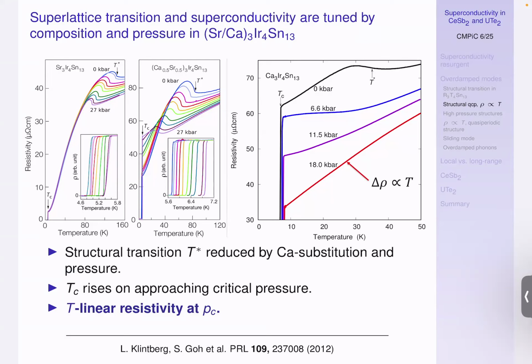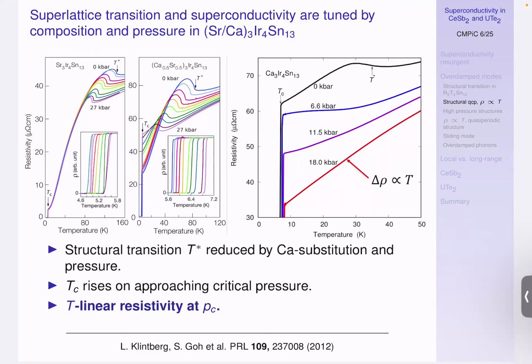If you apply a magnetic field, it suppresses superconductivity, but we haven't really got good data to analyze the power law down here. But there's actually a problem there as well, which is a fundamental issue in a lot of materials like that: applying a field also changes the normal state resistivity. It doesn't just unmask the normal state underneath the superconducting state. If you apply a magnetic field to get rid of superconductivity here, you'll find the resistivity also changes up here. So it's not necessarily all that telling. It's not that high, but it's still of the order of 7 Tesla. Maybe, I don't know, don't quote me on that, it might be higher than 7 Tesla, but it is significant.